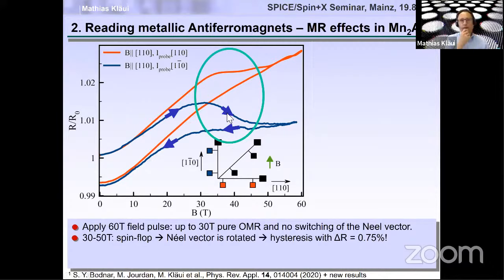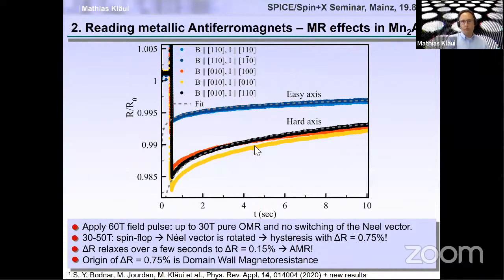Now the question is, if we go back to zero, it turns out that initially the resistance change is much larger, like 0.75%. But before, we saw that the AMR is only 0.15%. So where does this difference come from? It turns out that if you wait for a few seconds, a large part of the resistance recovers to this 0.15% value, meaning that initially we have a larger change of the resistance, but after a few minutes or so, we are back at this 0.15%, which is the AMR.